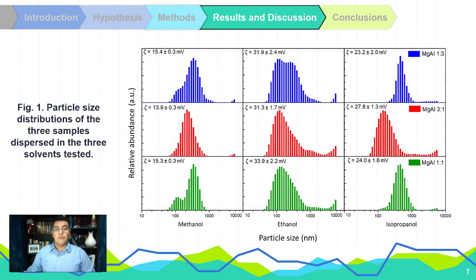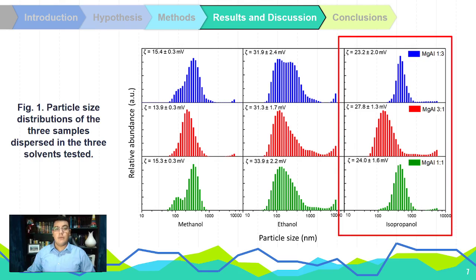As the results, we first show the particle size distribution of our three materials in the three solvents tested. As we can see, isopropanol was the best solvent, because it's the one that led to the formation of a dispersion with a better homogeneity of the particle size. It also had a zeta potential in the optimal range for an electrophoretic deposition.